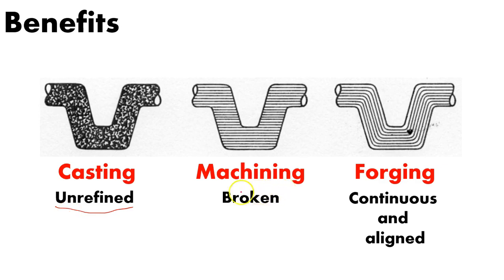Here at machining, which is a lot similar to stamping in that you're actually removing material. And stamping is a little more abrupt, but you're still removing material, and you're breaking a lot of the grains. You're breaking a lot of the grain boundaries in order to form the shape that you want to form. So again, a lot more likely to have fatigue failure with a machined process. Not nearly as ductile as forged.